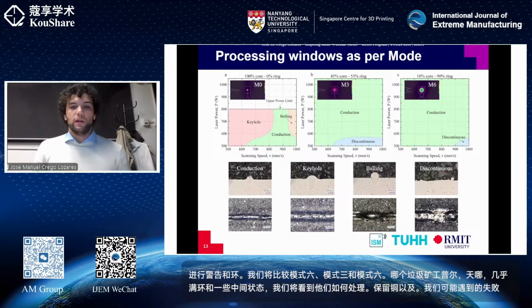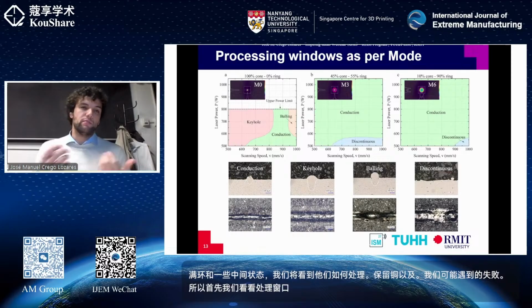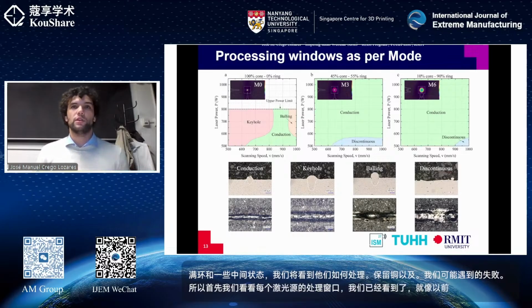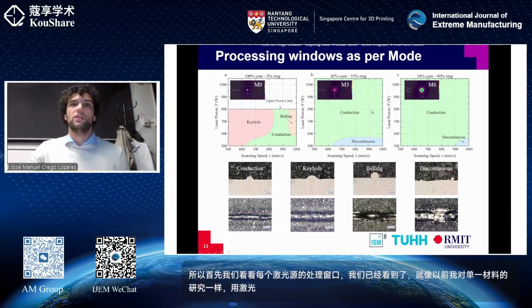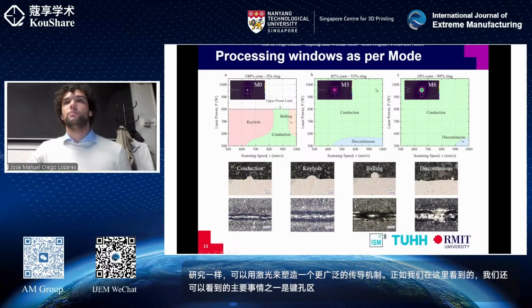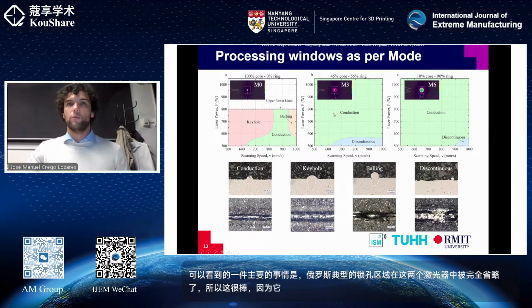So first we look at the processing windows for each laser source, and we've seen, as in previous single material studies with laser beam shaping, that a much broader conduction regime can be achieved, as we see here. One of the main things that we can also see is that the keyhole region that is typical from Gaussian is completely omitted for these two laser sources. This is great because it provides us a much broader window that we can work with. And yeah, that's mostly it from here.